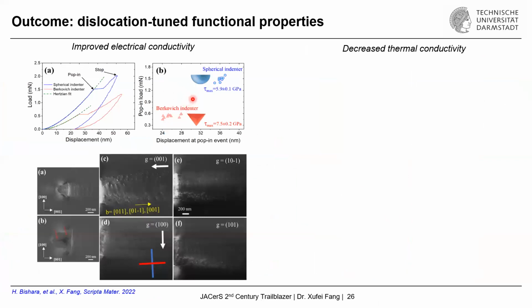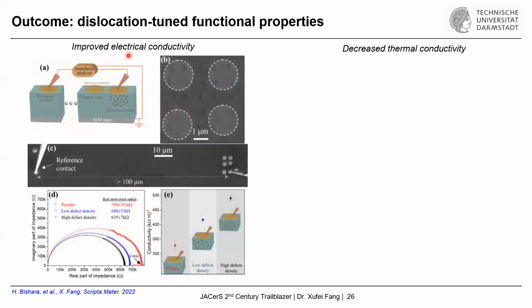And I would also like to take a few more minutes to show you the dislocation-tuned functional properties. And this is the technique I briefly introduced at the beginning, using the nano-indentation technique for the pop-in studies, where we can engineer a lot of dislocations, overlap the indents, and have a larger plastic zone. And then we can also see that the dislocations we engineer at room temperature actually can improve the electrical conductivity by almost 50%. And another case is to use the pre-engineered dislocations to decrease the thermal conductivity, which is also very important for the thermoelectric figure of merit.